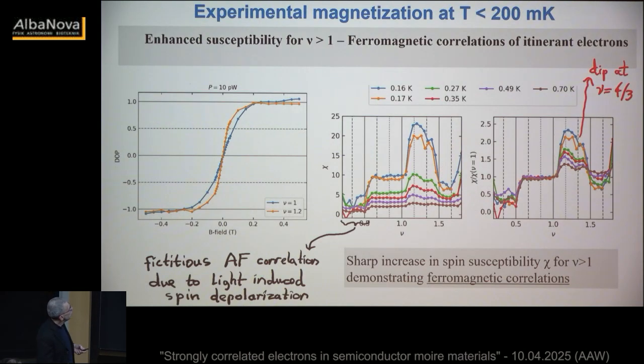All right, so before making the story too long, what we find is that at mu equals 1, and for a large filling factor range, from 1 to about 0.5, we find this almost exactly blue curve, which is the paramagnetic spin susceptibility. Of course, with a large enough magnetic field, it saturates because we polarize.